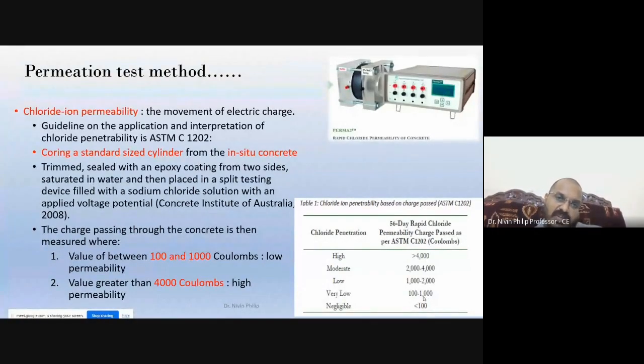So in a forensic investigation, the use of this is that when deterioration happens, the porous nature will increase, or the quality of the concrete will be lesser. In that case, we have to identify whether the rebar is corroded due to the poor quality of the concrete. From this test, we can identify the porous nature of the concrete.